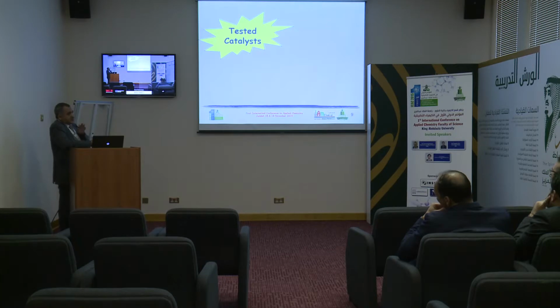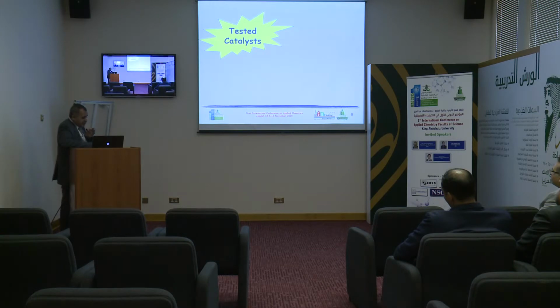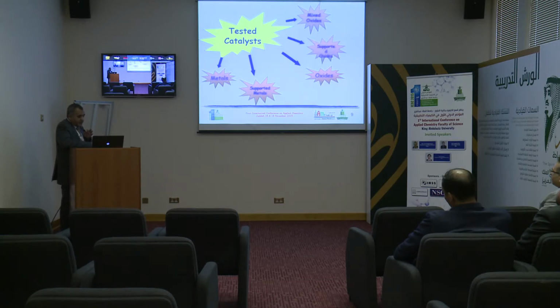Our work is focused on the direct catalytic decomposition. There are many catalysts tested for this reaction which showed really good activity. Some of them metals, supported metals, oxides, mixed oxides, supported oxides, and zeolites. Up to date, the applied catalysts in this type of reactions are the zeolites, especially the iron ZSM5 type, and also the mixed oxides like spinels, cobalt oxide based catalysts.